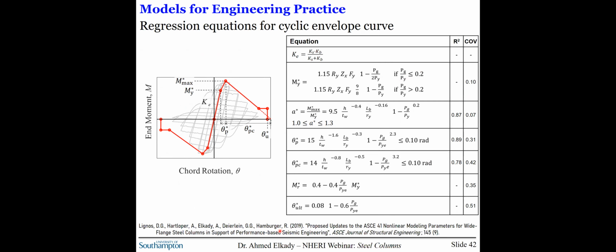Here are, for instance, the equations for the proposed first cycle envelope curve. And one of the key updates here is that, instead of providing constant rotation values based on discrete bins of slenderness ranges or loading ranges, these equations capture the variation and the change in all the parameters for all ranges of loading and geometric values. So it doesn't lump together different cross sections in the same bin. Otherwise, you are getting here the full variability in the parameters.